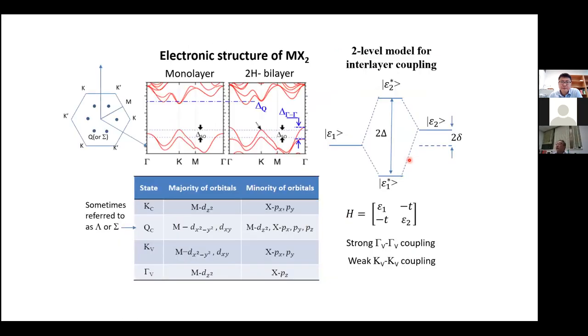All right, now let's look at when you have a heterostructure, right? First, you can assume the electronic structures of these two constituents are just independent. But that cannot be true, otherwise the monolayer to bilayer transition cannot have this direct gap to indirect gap transition. This happens because of interlayer coupling, say at the gamma point, which is very large, and it splits the states at the gamma point and pushes the valence band maxima above the K point. So you're going to see that the interlayer coupling cannot be ignored.